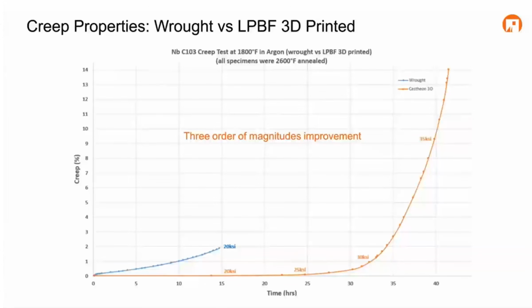So I talked about not just ultimate or elevated temperature tensile strength, but also creep performance. You can see here the comparison between the wrought material tested at 1800 degrees Fahrenheit in an argon environment. The wrought material was annealed, as was the AM material, at 2600 degrees Fahrenheit. And you see whereas this specimen failed at about 2% creep after 15 hours, we saw no measurable creep at 15 hours or even out to 25 hours.